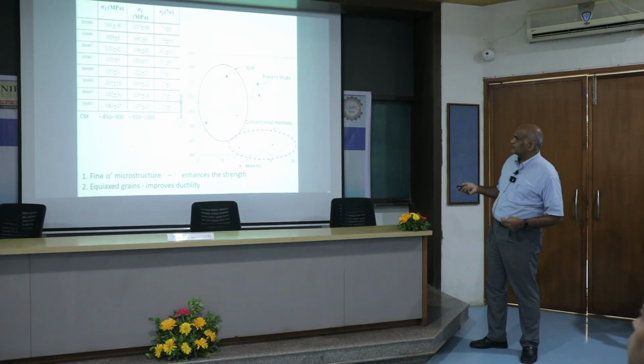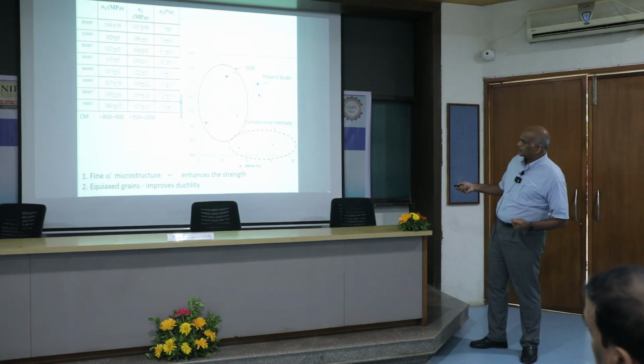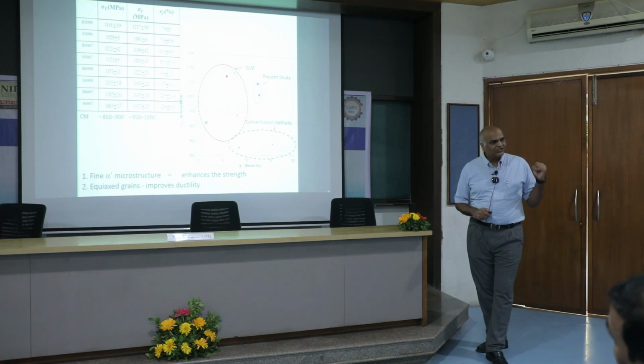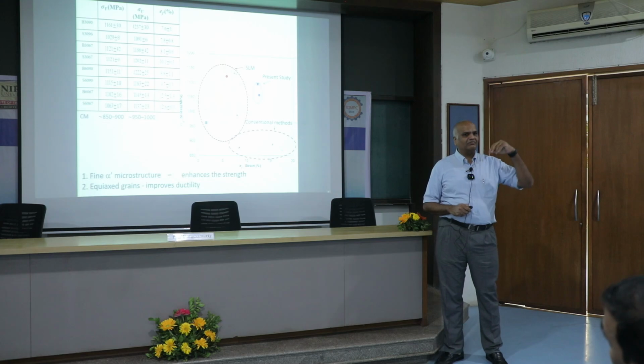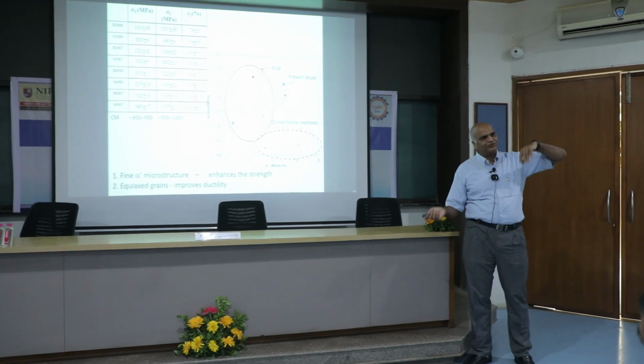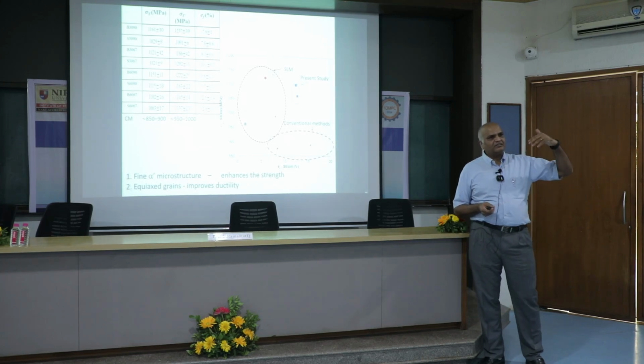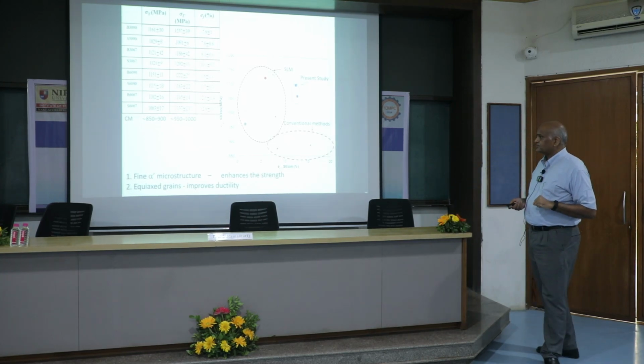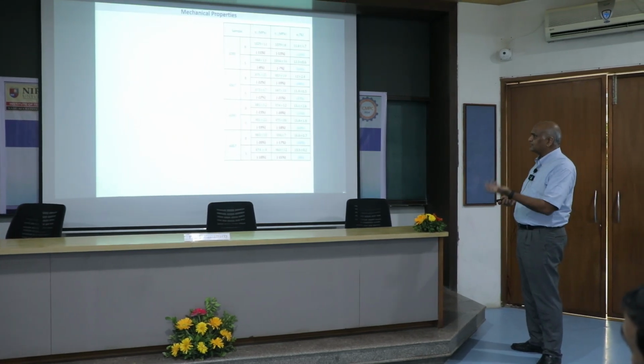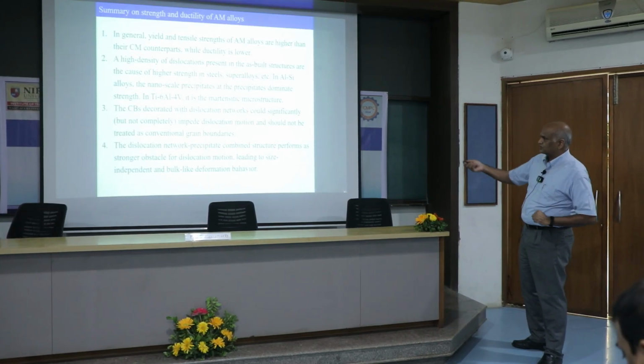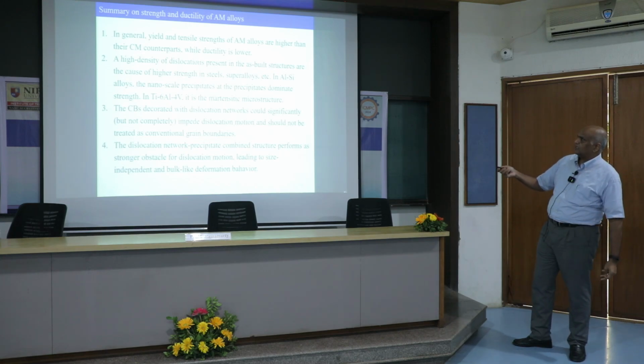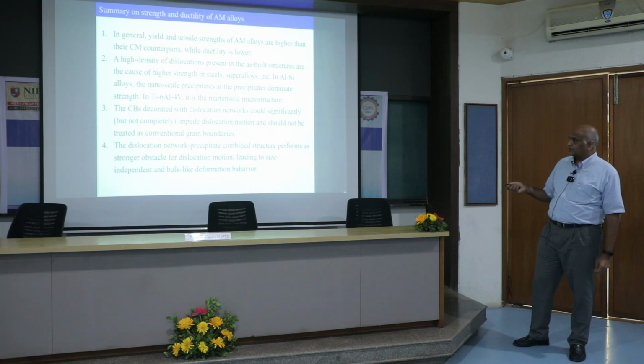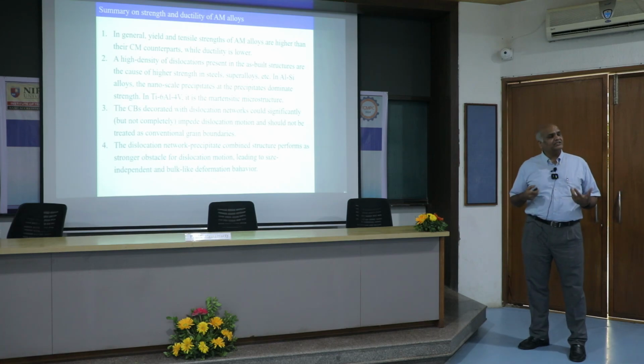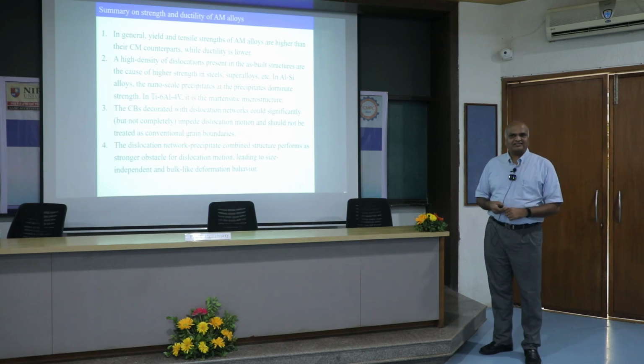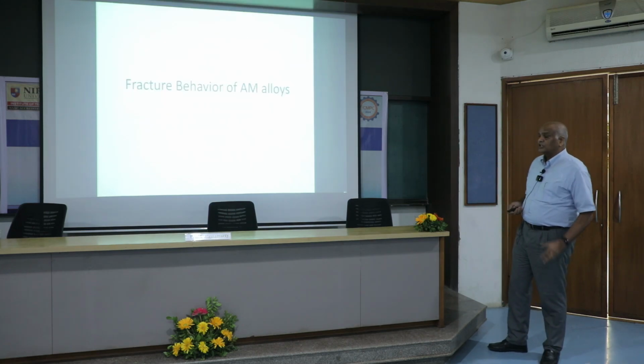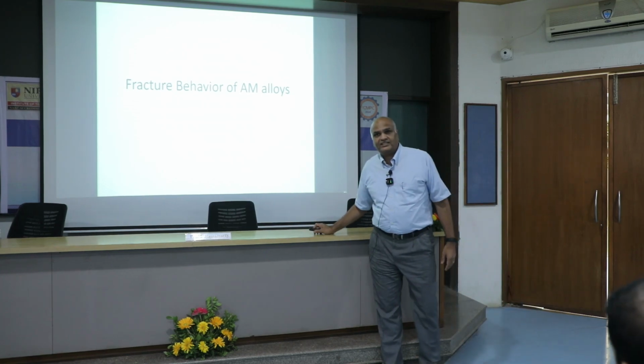So for example, if you look at conventional methods, compared to that, we get high strength. Again, the same story. When you take a 3D printed part, whether it's Ti-6-4, aluminum alloy, steels, everything, the strength will be higher. Typically, ductility will be lower. And then we can also heat treat it, change the mechanical properties, etc. So this is the summary: the yield and tensile strengths go up, ductility comes down. The strength enhancement is because of the dislocation density being higher, and that's also the reason why you have lower ductility. Now, it's not enough that you have high strength, right?